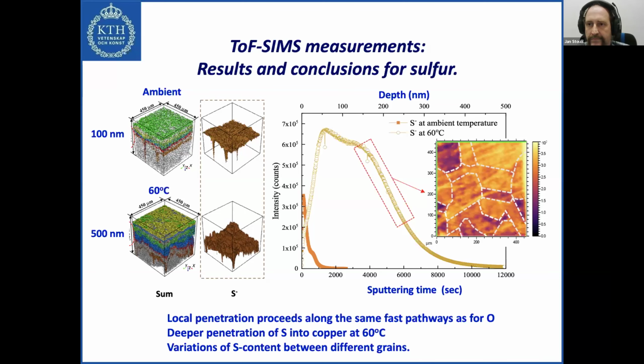Yeah, we have, of course, also the ant-nest corrosion, which also shows this type of behavior, as I also showed you, and something called one-dimensional worm form corrosion, which has recently been published in the literature. And both of these suggest that there is quite an enhanced penetration at elevated temperature. But again, it does not follow any simple Arrhenius plots at this point, as we can see it.